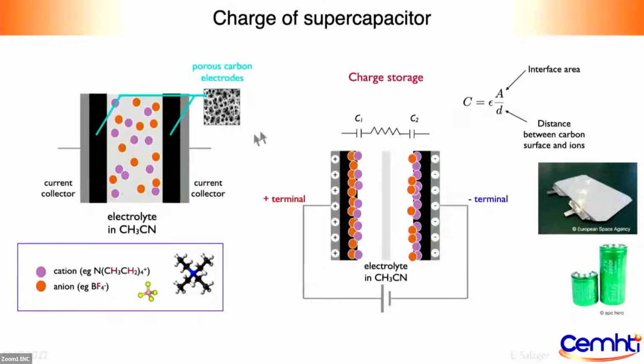So as I said before, the supercapacitors are based on an electrical double layer forming at the surface of the electrodes as we charge them positively and negatively. So here we have nanoporous carbons as electrodes, and this charge organization stores the energy in the form of a capacitance. And this capacitance is related to the distance between the ions and the surface.